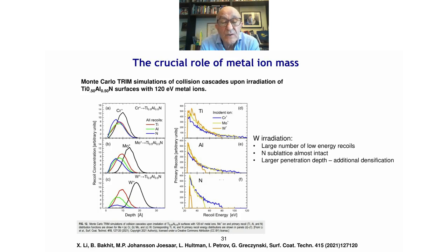If you look at the energy distribution of the particles, the top graph, you can see the chromium extends to very high energies because of the high mass. And then if you look at the yellowish color, the tungsten, it is low energy and high number. So larger penetration depth with tungsten, nitrogen lattice almost intact. Look at the bottom curve, nitrogen, almost no displacement, and a large number of low energy ions. So these are the benefits, the specificity of using heavy metal. Next one.